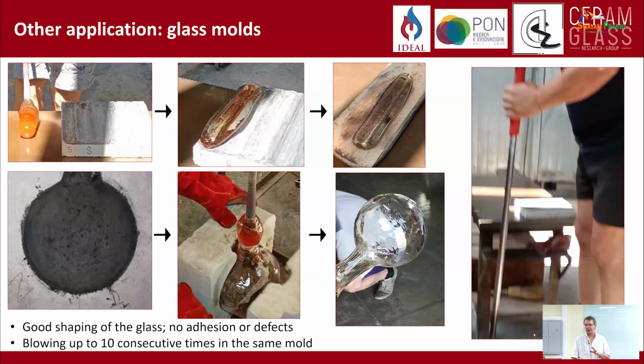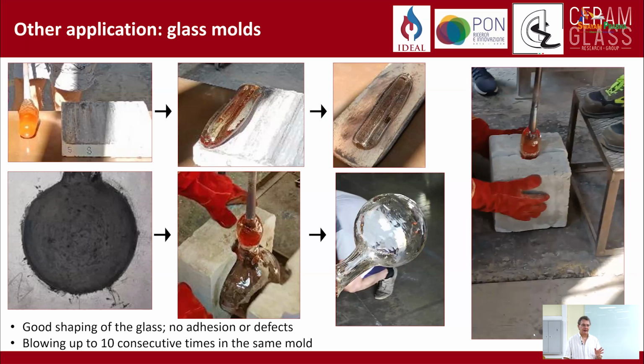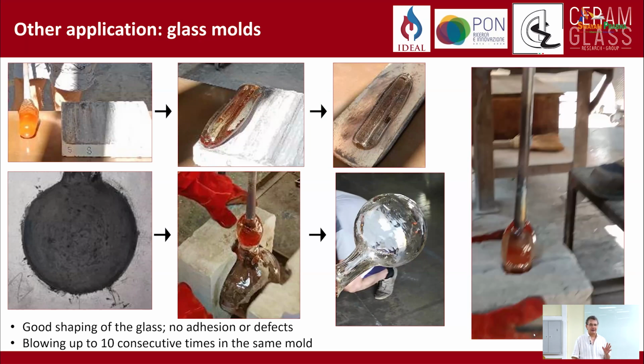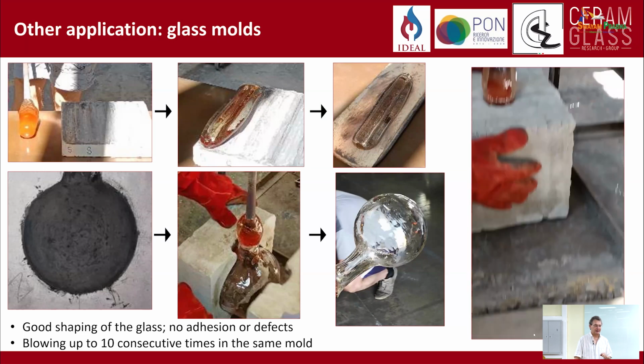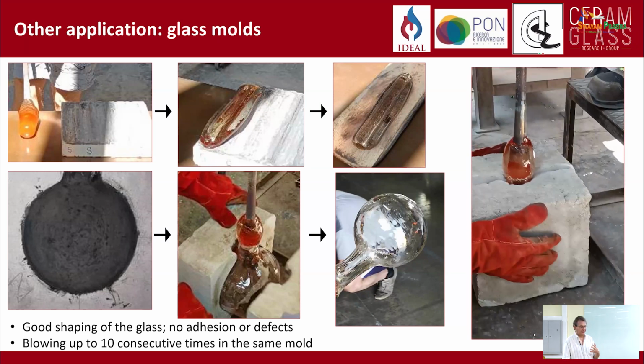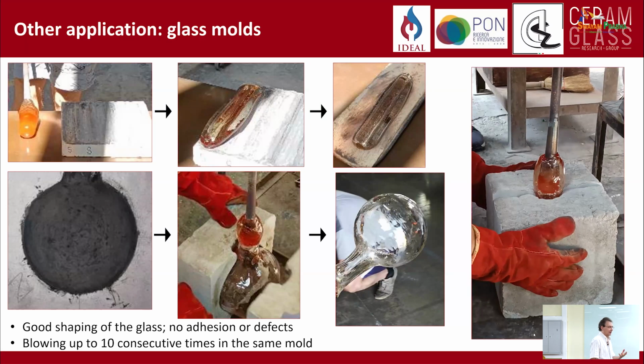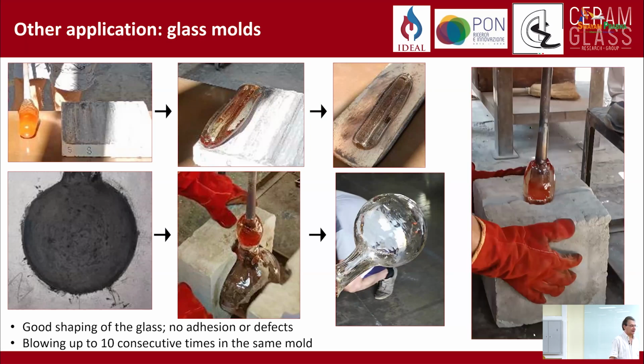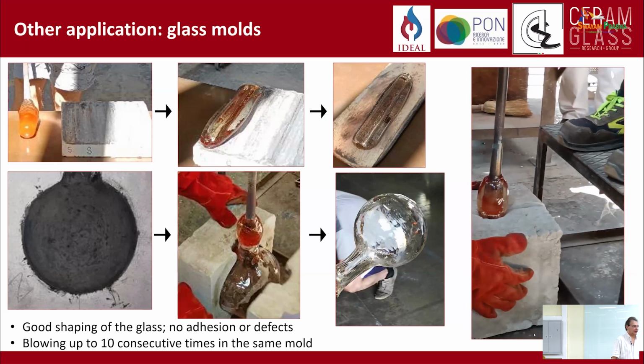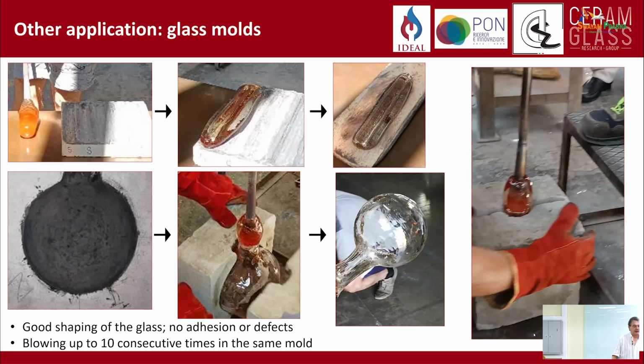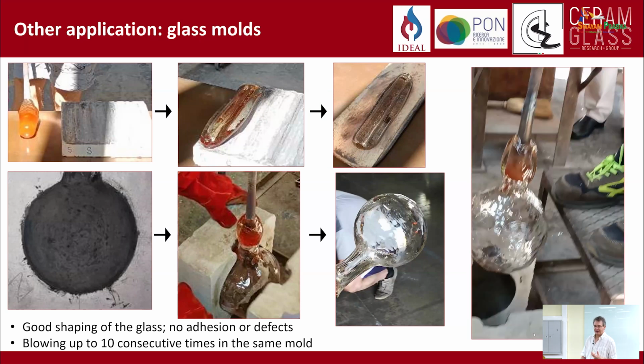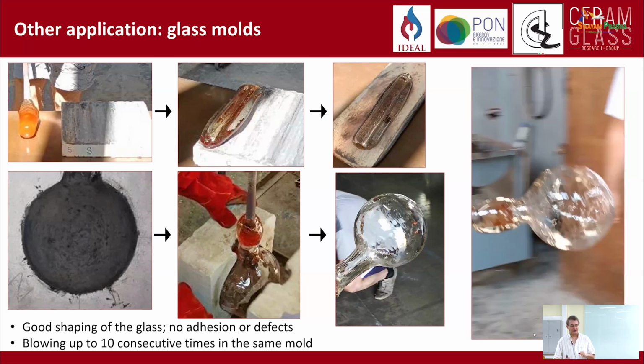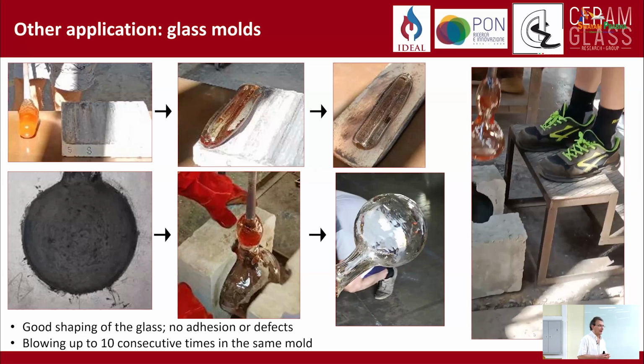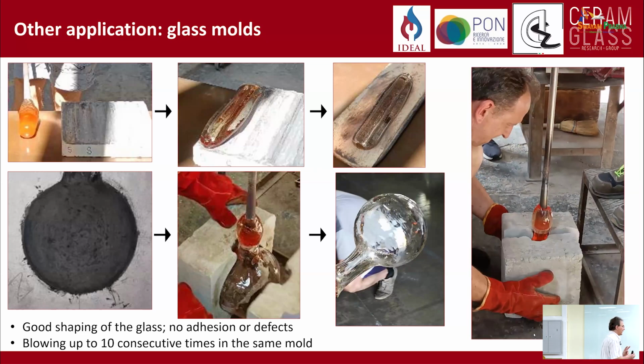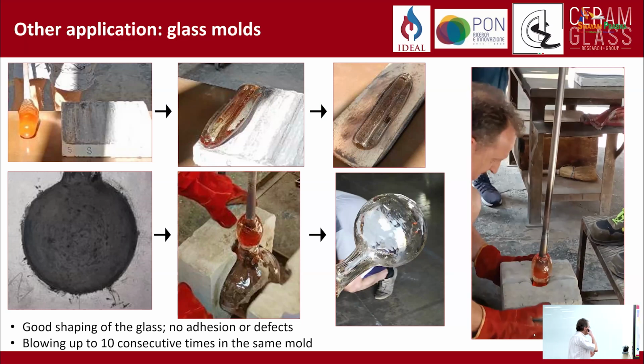And the reason, I assume, is related to the way the wood chars and can thermally insulate the rest of the mold without it burning out while you're using it. And there are sustainability issues with this type of approach because there are not many pear trees available these days for making molds with a certain size. So we actually have two regional projects for making molds for molten glass.